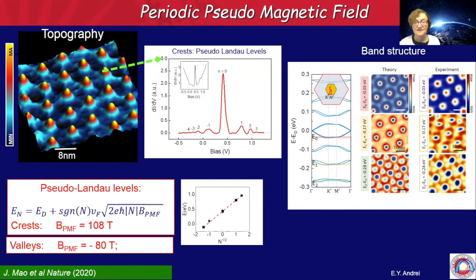And then you can look at a band structure. This is a theoretical band structure. You indeed have flat bands here, which is what these peaks are telling us. So we have created a system with flat bands. Now, unlike the blister that I showed you before, where the pseudomagnetic field was concentrated in one point and was not spreading over the entire sample, here we have a periodic structure of pseudomagnetic field, and that's why we have flat bands that spread out through the entire sample. Here you can see how they propagate along the sample, both experimentally and theoretically. For each one of these bands, you can see their distribution within the sample.